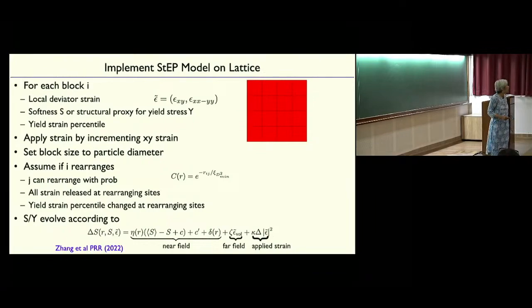with that length scale. But that doesn't depend on your cooling history or annealing history? For example, if you do it better anneal? It does, because it depends on the correlation length of softness, and that depends on that.